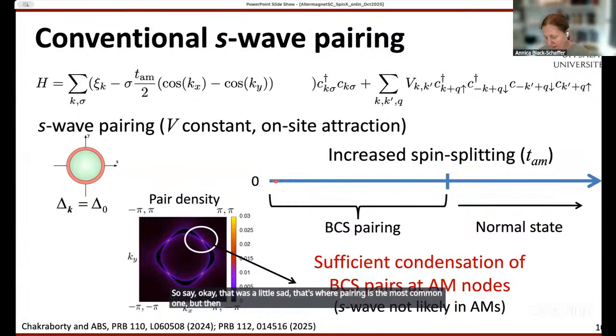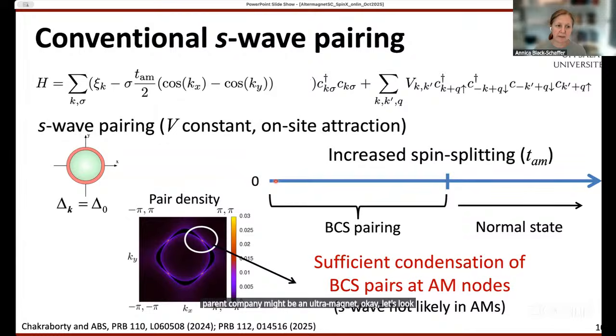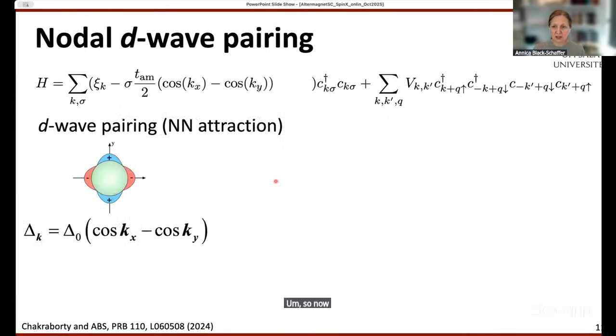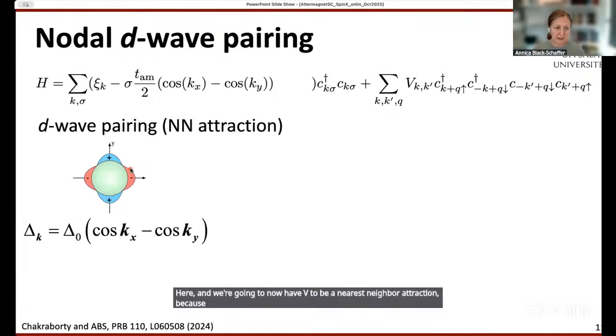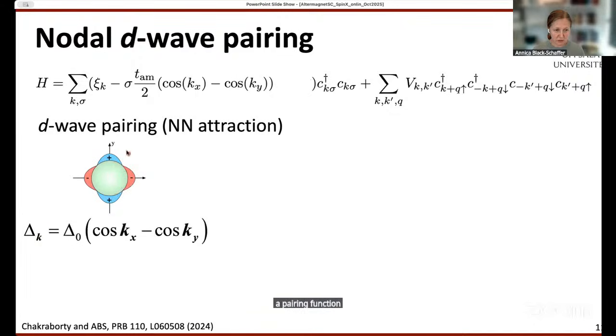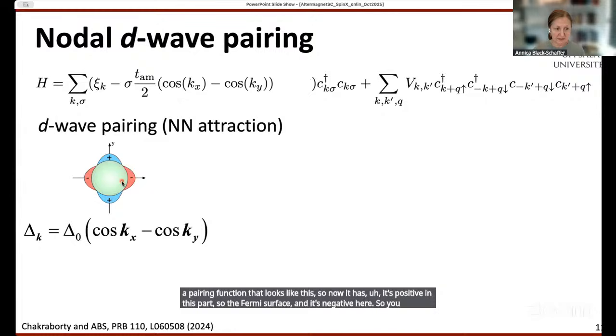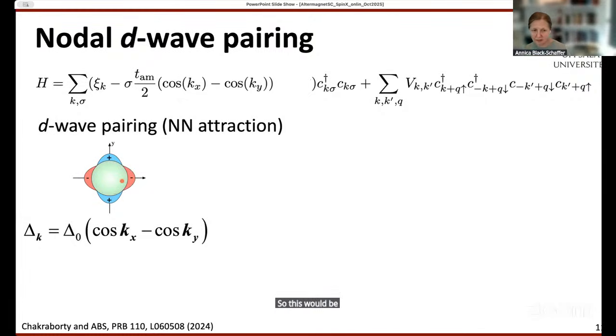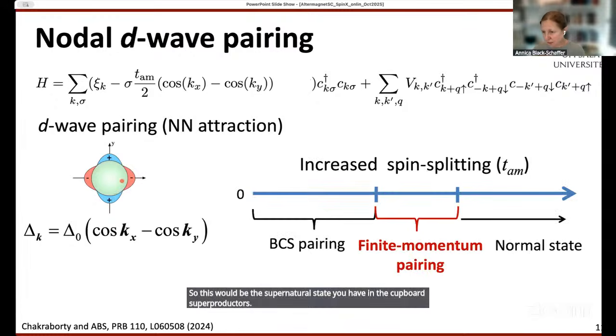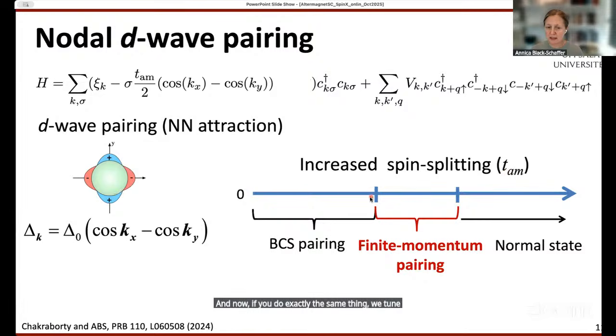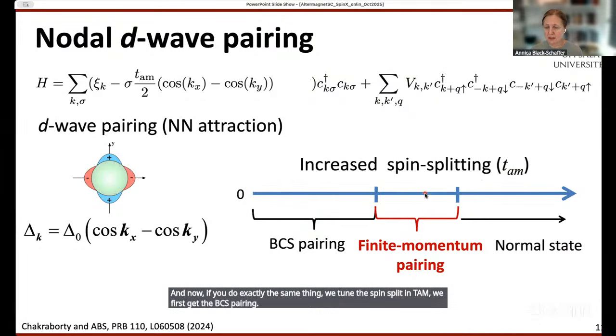But then we started thinking, well, D-wave pairing is pretty common too, especially in the cuprates. And there was this cuprate parent compound that might be an altermagnet. So okay, let's look at the D-wave pairing too. Now the only thing we change is this V, and we're going to have V be a nearest neighbor attraction, because if you do that, we get a pairing function that looks like this. It's positive in this part of the Fermi surface, and negative here. So you see it has a clear D-wave symmetry. This would be the superconducting state you have in the cuprate superconductors. Now if you do exactly the same thing, we tune the spin splitting TAM, and we first get the BCS pairing, then we get the finite momentum pairing, and eventually we get the normal state. So now we do indeed get this finite momentum pairing here.